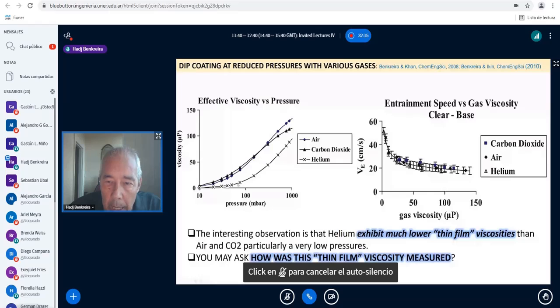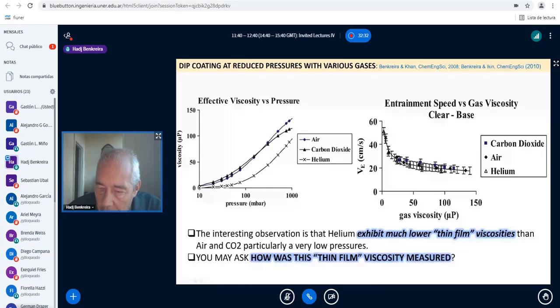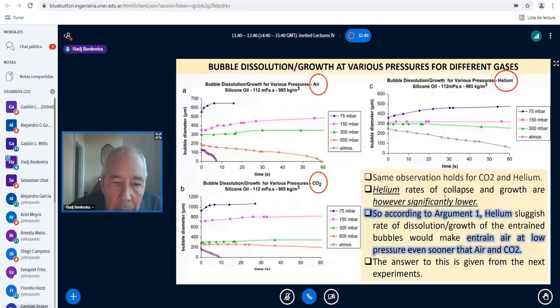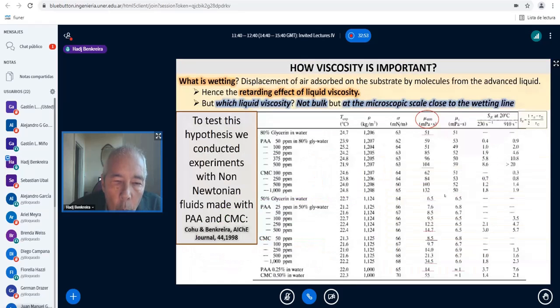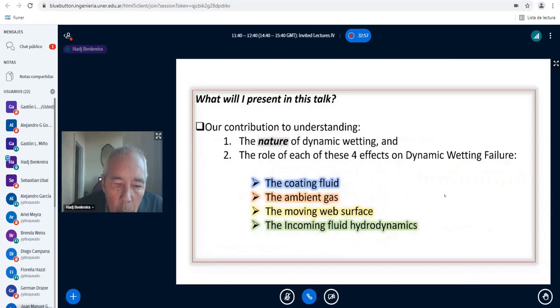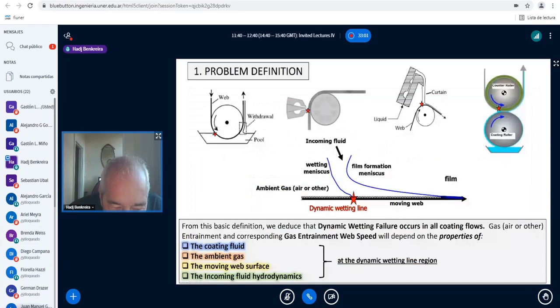And once we correlated the entrainment speed versus gas viscosity, we could bring all the curves together into a single line of gas entrainment speed versus viscosity. But then, which viscosity are we talking about? We are not talking about the bulk viscosity of the gas. Again, we are talking about the thin film viscosity of the gas. And I go back to the definition that I started with at the very beginning. What matters is the viscosity of the gas very, very near the surface, not the viscosity of the gas in here. And how are you going to measure that viscosity? That's the next thing.